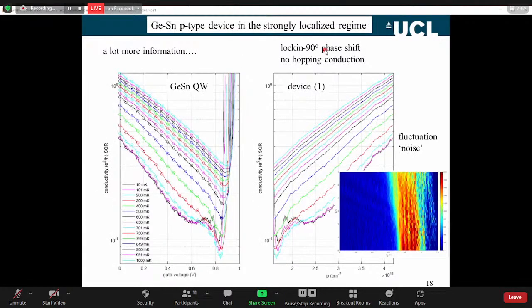When we cool these devices down in the fridge, it's actually quite dramatic. We measure the conductivity. This is the conductivity at constant temperature. This is at 1 millikelvin. As we deplete the device, the conductivity drops. And then at some point we just lose the device. It just goes very, very resistive. The way we measure them becomes a problem. We use small currents. We get things like phase shift in the signal.